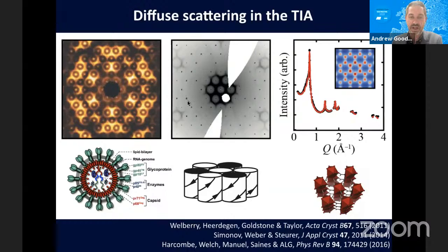In the middle is that trisamide nucleating agent that I showed you, and on the right-hand side is the magnetic neutron scattering from that terbium formate. What you see is this same characteristic honeycomb-like diffuse scattering in each case. In the case of the terbium formate, we're just looking at the powder average. So this signature that you see here, with the nuclear Bragg peaks missing, is really just the orientational average over what you have in the middle.